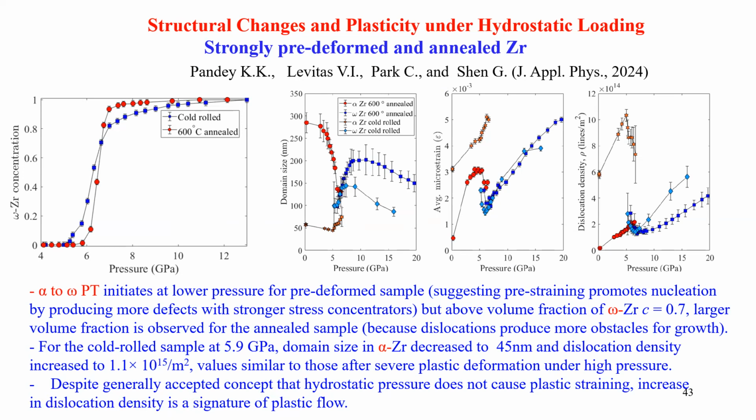So each one obtains own sample with different prehistory, which is unknown. And if not characterized, then this goes to scatter because the microstructure for each sample is different. Also, even if you anneal sample, one of the most popular methods to make sample for diamond anvil cell is to scratch tip from a big chunk of material.